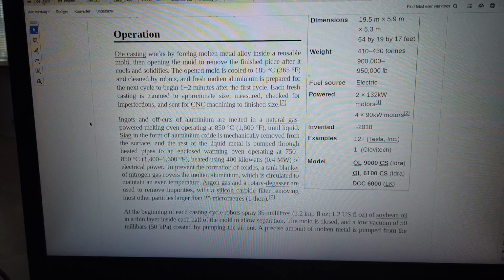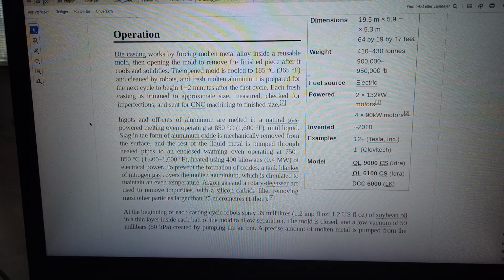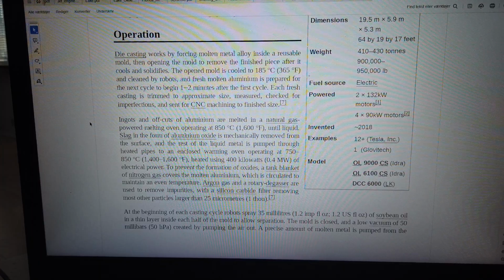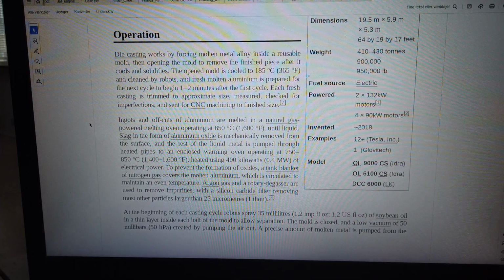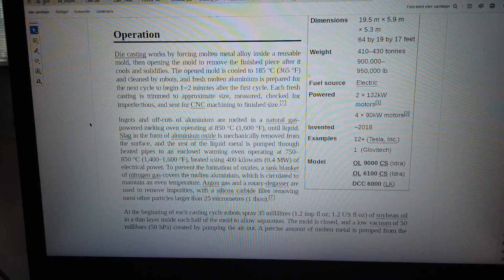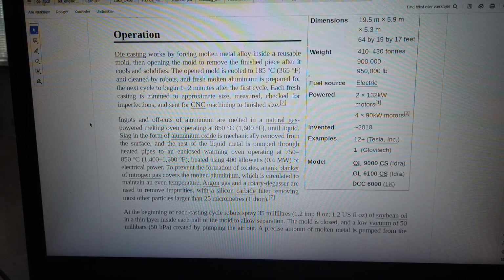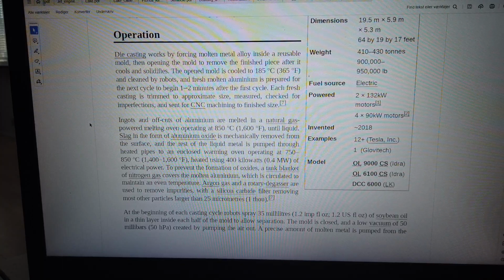Ingots and offcuts of aluminium are melted in a natural gas-powered melting oven operating at 850 degrees Celsius, 1,600 degrees Fahrenheit, until liquid. Slag in the form of aluminium oxide is mechanically removed from the surface, and the rest of the liquid metal is pumped through heated pipes to an enclosed warming oven operating at 750 to 850 degrees Celsius, 1,400 to 1,600 degrees Fahrenheit, heated using 400 kilowatts, 0.4 MW, of electrical power.